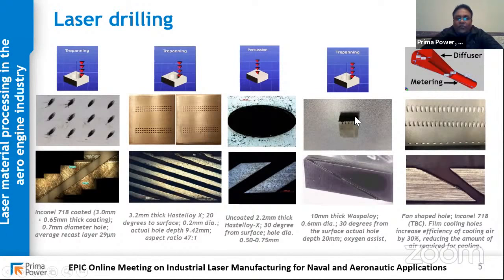There are also some applications where you drill very deep holes. This is an example of 10 millimeter thick Waspaloy, drilled 30 degrees from the surface, so the actual depth of the hole is about 20 millimeters. The thing to point out here is how parallel the hole is from top to bottom, with very little taper and very little recast layer. So these are some of the examples, from TBC to very thick material, of laser drilling currently being used in aerospace.